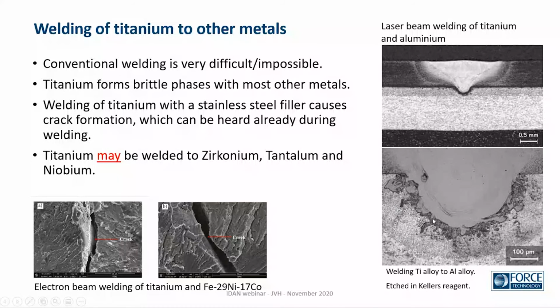A lot of research is done on trying to solve problems by laser welding, because the process is faster and the amount of material melted is less. So that might solve some problems. And in this example, we have titanium to aluminium. From first glance, it looks like we have got a joint. It sticks together, but when we look into the structure in the weld zone, we can see some very odd phases around here, and I would certainly expect this to have poor mechanical properties. So it sticks together, but as a joint, it might be limited in application.